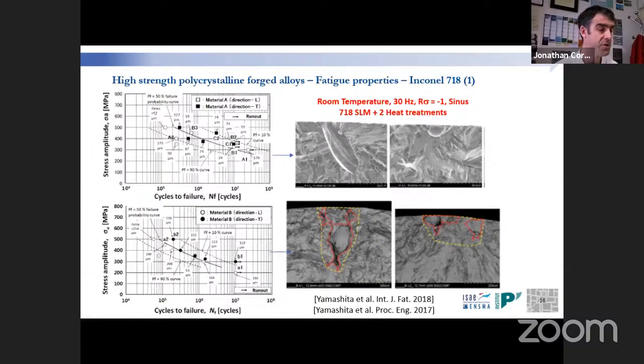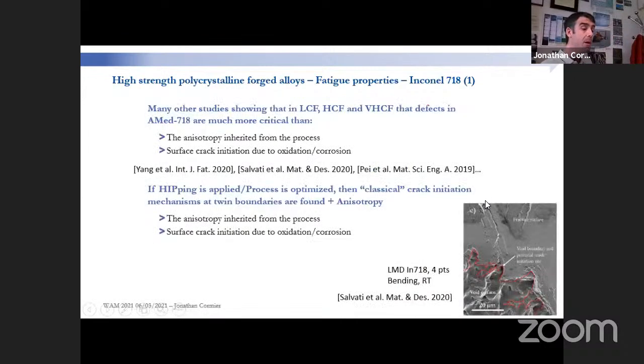So typically lack of fusions, pores, and as long as we have this kind of defects inside the materials, the anisotropy, the way the specimen is built, is not really important. I mean, in terms of texture, for example. So if we want to be able to characterize intrinsically the properties of this class of material, we need to get rid of defects. That's also something interesting for wire deposition, being a process in which we know that we have a lower porosity in terms of volume fraction and or size.